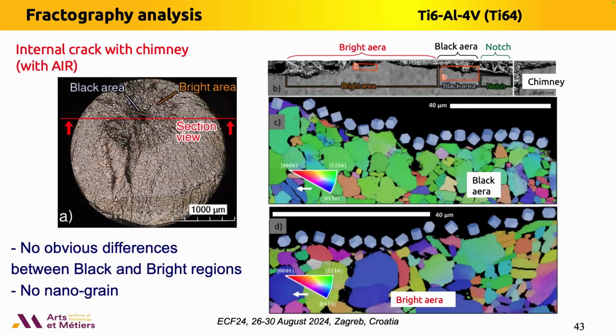And the last slide about the mechanism is the following. We have cut the defects here and observed the corresponding section by EBSD. We have observed below the fracture pattern that you can see here, from the chimney to the notch and then to the bright area. We have not observed any difference between the black and bright regions, and we didn't observe nanograins or nanopores. No modification because we are in air.